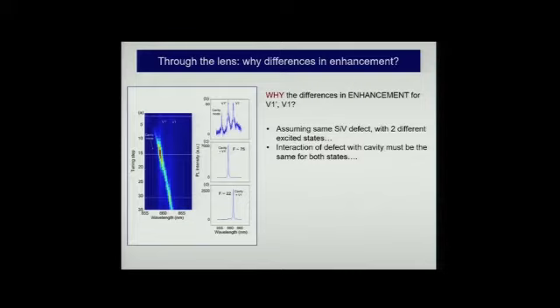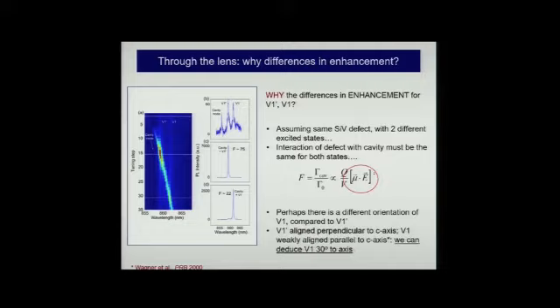The probability of what? The transition from 1 to 3 and 1 to 2 is different. And so it could be that the matrix element, yeah? We think that it may have something to do with that. So Q over V, that's the cavity. That's the same. So any enhancement, if we look at the Purcell factor, Q over V should be the same for both of them. So in our simple-minded way, if there's any difference, you're talking about probability. Maybe this is the matrix element. And maybe this difference means that there's a different orientation of the higher energy excited state relative to the lower energy state.